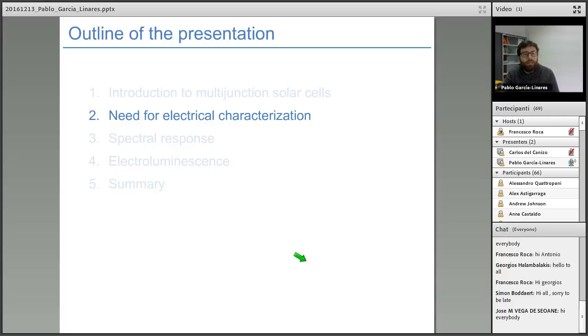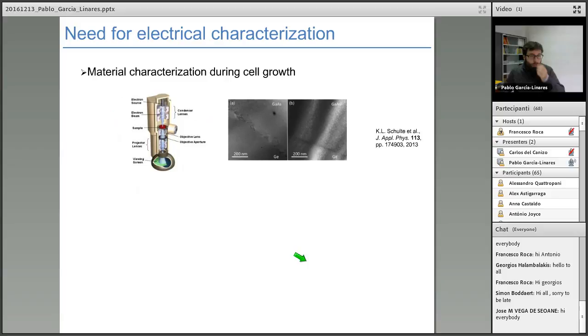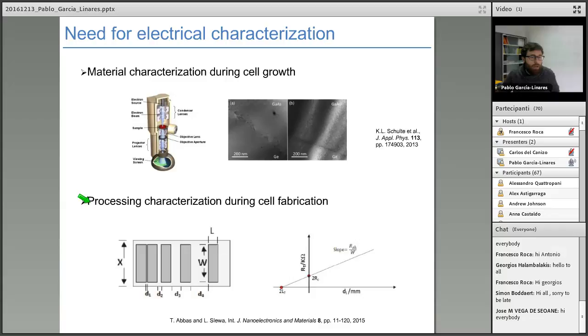Let's review why we need electrical characterization in general for solar cells and in particular for multijunction devices. During the growth of these 3-5 material structures — sometimes grown on a germanium substrate — they require an epitaxial reactor and a quite complicated growth process. Such growth process has to be characterized, for instance with transmission electron microscopy, to provide feedback on the process. Another requirement is once the solar cell layer stack has been grown, the engineer needs to fabricate the device by implementing electrical contacts, mesas, and anti-reflecting coatings.